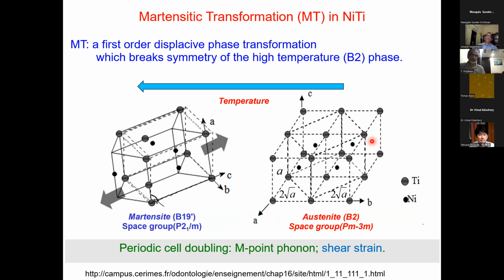Fundamental to this shape memory effect is also a structural phase transition. And I introduced to you earlier, it's a martensitic phase transition from cubic B2 phase called austenite phase to martensite B19 prime phase in nickel titanium. You will see this phase transition involves cell doubling, meaning the unit cell of the cubic phase doubles in the low temperature phase, and also large shear strains. So how do we understand this phase transition and develop a model for it?